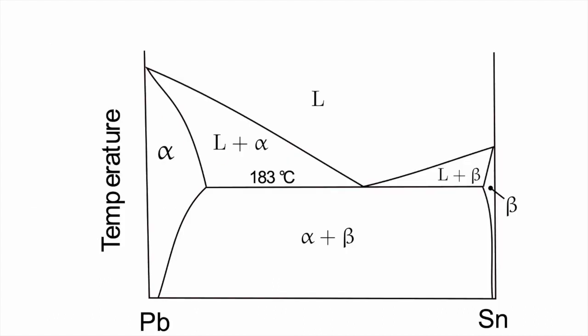This phase diagram for the lead-tin system is quite different from what we had for titanium and molybdenum, where we had complete solid solubility and liquid solubility across the concentration range. Here, the solubility of tin in lead is given by this phase boundary. Beyond this concentration, we would get precipitation of beta. And similarly, this phase boundary here defines the solubility of lead in tin. And if you exceed this concentration, we would get the precipitation of alpha. So we get a mixture of two solid phases between these two phase boundaries.